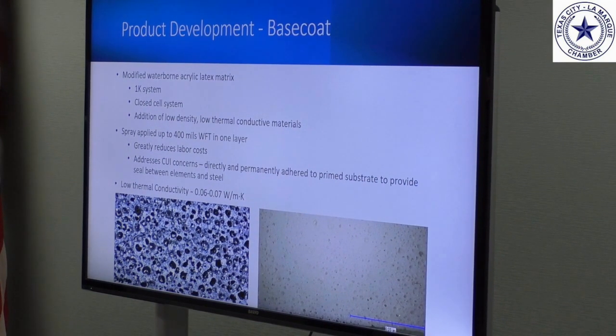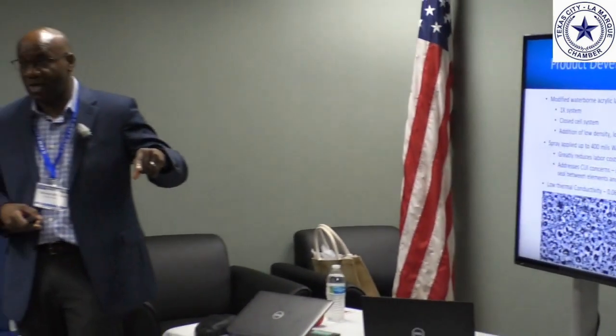And the key here is that because we have intimate contact with the metal substrate, we do a primer, of course, on the metal substrate. There's a seal between the steel and the insulation material. When you have mineral wool, there's an air gap between that primer surface and the insulation. That air gap, you have water in that air gap, you have salts in that air gap, they penetrate the coating, percolate through the primer coat into the metal, and cause CUI. In this application, there's no air gap, so you eliminate CUI because the conditions for CUI don't exist if you don't have that air gap.